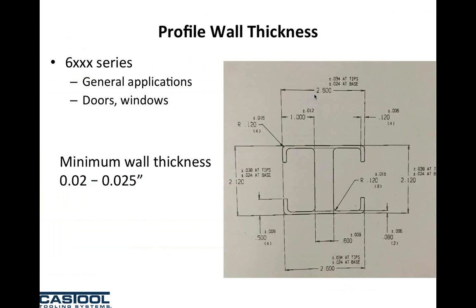When we start looking at wall thickness, flow stress also gets involved. And I think this is something that a lot of people forget. If you're doing a standard window shape or something today, you may have minimum wall thicknesses down as low as 20 to 25 thou. And 6063 is an adequate alloy for doing this.